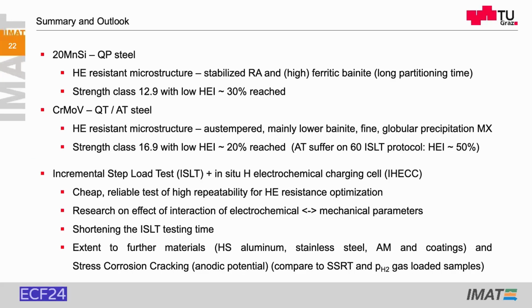Well, the summary: the hydrogen resistant microstructure for quenched and partitioned steel is a stable retained austenite with a ferritic bainite, achievable with a long partitioning time. The strength class 12.9 could be reached with a hydrogen embrittlement index of 30%. For chromium, molybdenum, vanadium, the hydrogen resistant microstructure is austempered lower bainite with fine globular precipitates. This is wishful to reach the 16.9 strength class with a low hydrogen index.